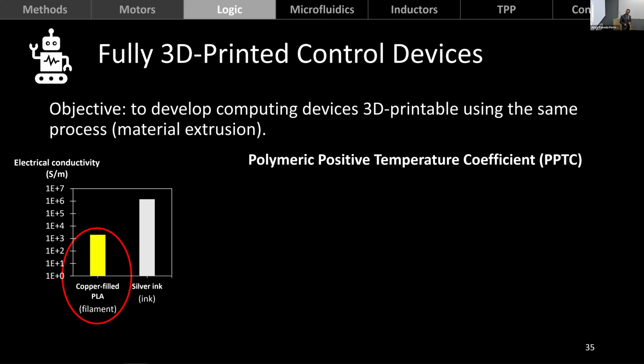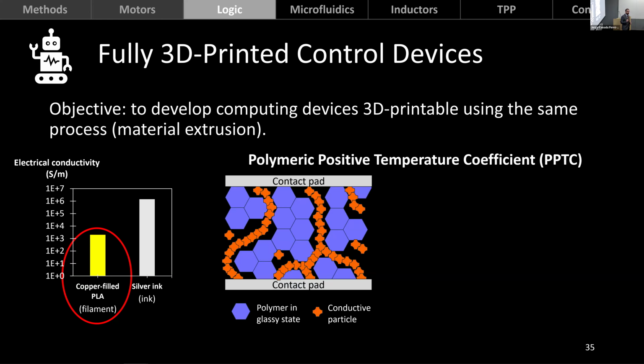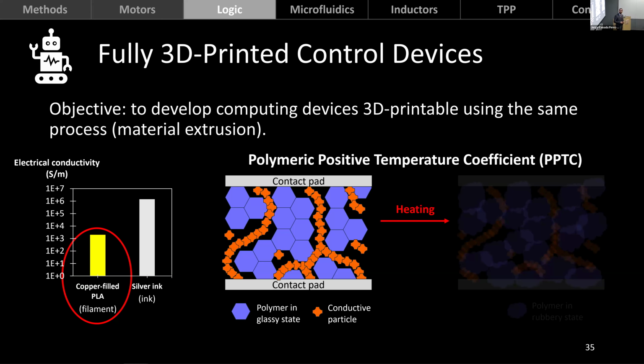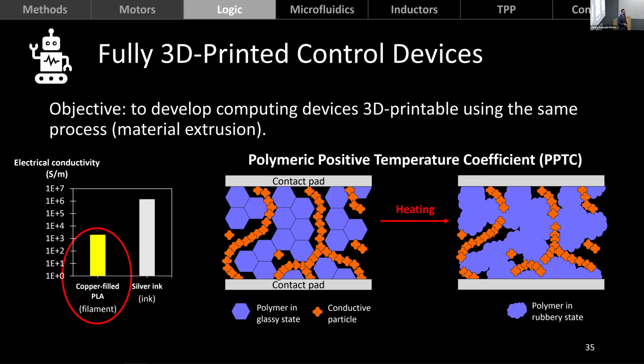And so this phenomenon is as follows. If we add conductive particles to a polymer, or to some polymers, they form conductive chains that effectively create a conductive path, making the whole polymer slightly conductive. Now, if we heat it up, then it's going to reach a point called the glass transition temperature, at which the polymer becomes much more susceptible to thermal expansion. And by means of that expansion, the conductive chains break, making the resistance of this device rise by orders of magnitude. Now, luckily for us, this is a reversible process. So if we let it cool down, the conductive chains reestablish themselves, and it goes back to its original resistance.